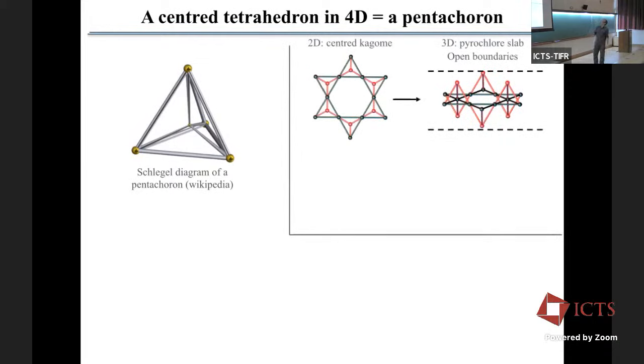So let's do a Gedanken experiment. Let's take a 2D centered kagome, okay? We're in 2 dimensions, we have the kagome lattice, and we put one site in the center. So you see this site makes a honeycomb lattice, and you have J1, J2 couplings. Now, take out these sites, and for the up triangles like this one and this one, you make them go in 3 dimensions above the plane. And for the 3 others, you make them move in 3 dimensions below the plane. And you obtain this structure, which is a slab of the pyrochlore lattice in the 111 direction, okay? But it's really a slab, which means it's still 2 dimensions. Locally it's a slab of 3D pyrochlore, but you have open boundaries.